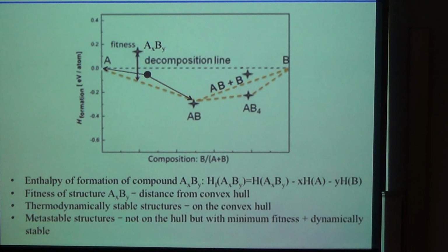Then we construct the so-called convex hull. So what is the convex hull? In this case, it's a binary compound, so X and Y are varying. The method is powerful enough that you can change the stoichiometry when you do this evolutionary crystal structure search. So this is the composition, the number that specifies a particular stoichiometry, and you have some structures that came out of your search. And we define so-called fitness. Fitness is the distance between this line and this particular point.